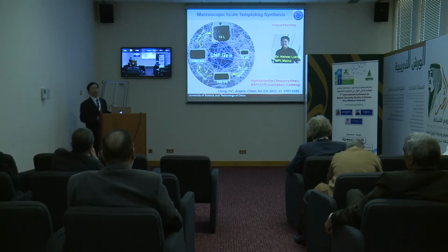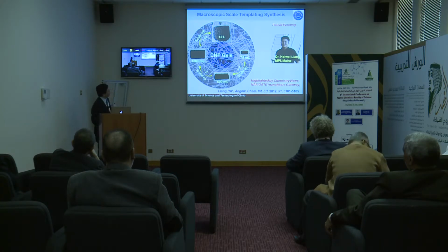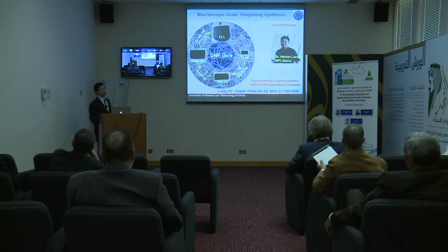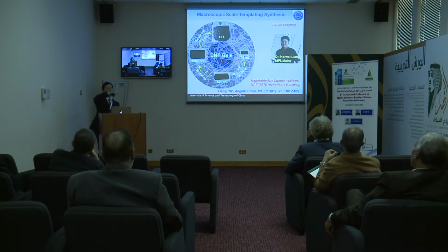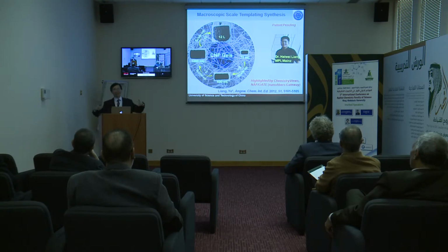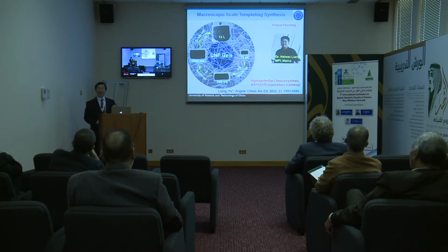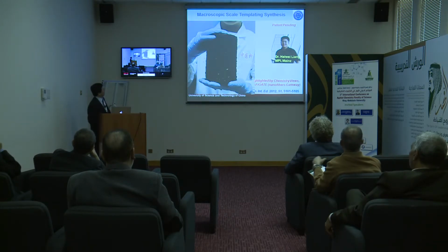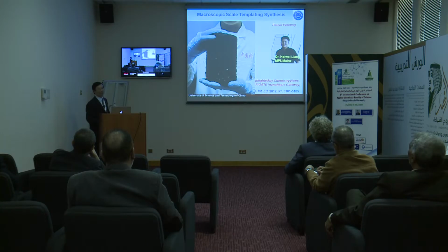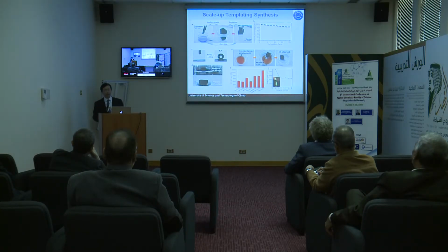of hydrogel or aerogel. We start from 75 milliliters. Now we can go to 12 liters. 12 liters is a really big one. We can even go to 20 liters. You can get 20 liters of nanowires. That means the macroscopic scale synthesis is indeed possible. So far, this nanowire network is really big, right? So that's good for future application for different material systems.